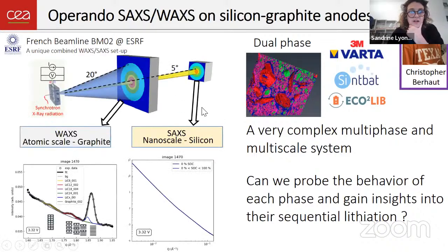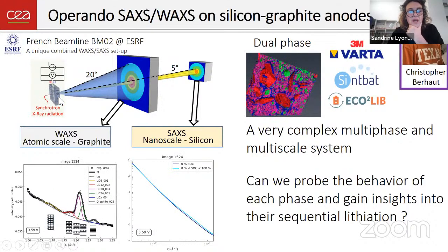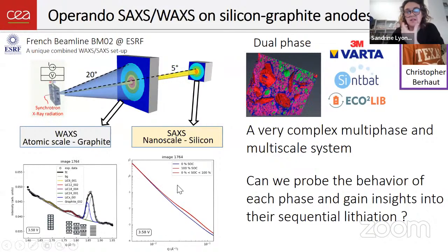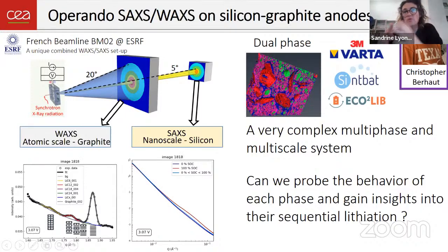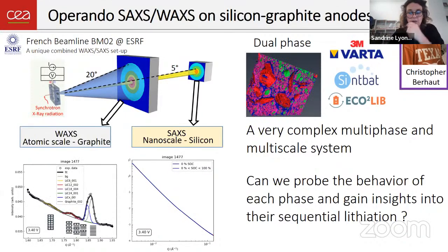And yes, we can. If we do this kind of experiment on BM02 at ESRF, we can have our nice battery working in the beam. And we have two detectors that simultaneously acquire data in real time. And that's highly interesting because on one hand, you can, by WAXS, have the crystallographic information that is telling you the state of lithiation of the graphite by the position of the different phases as Bragg peaks, as you can see here. And you have at the same time the SAXS data, which are telling you something about the silicon, which is this material that due to the alloying process is swelling a lot during the lithiation.